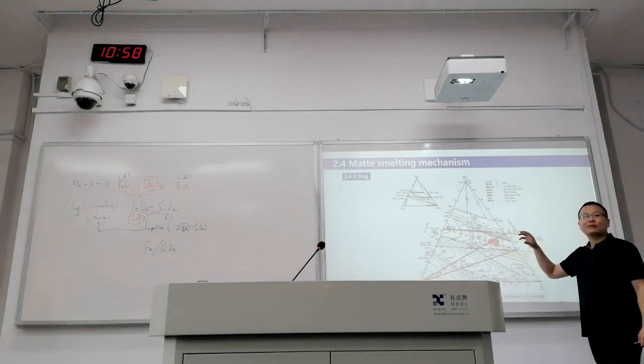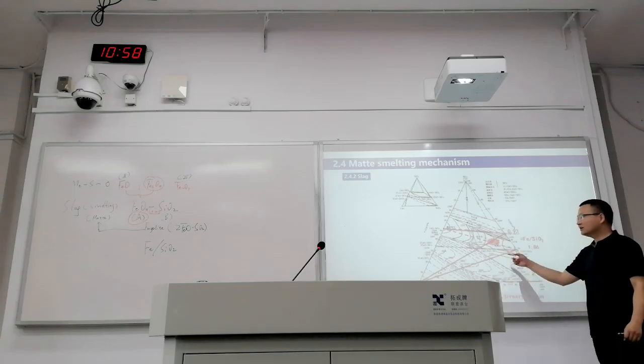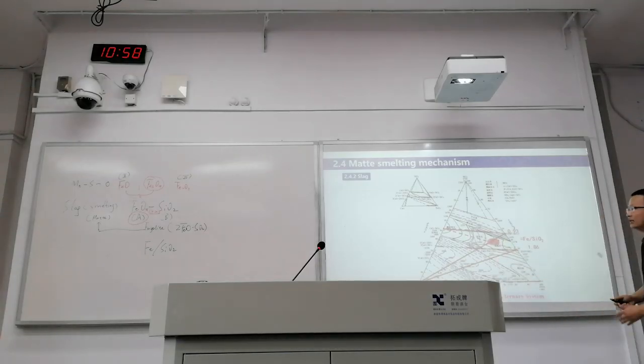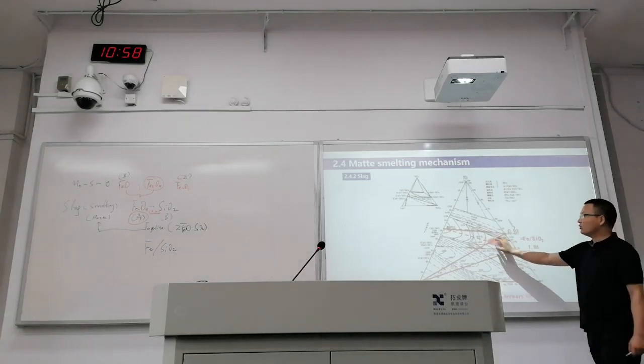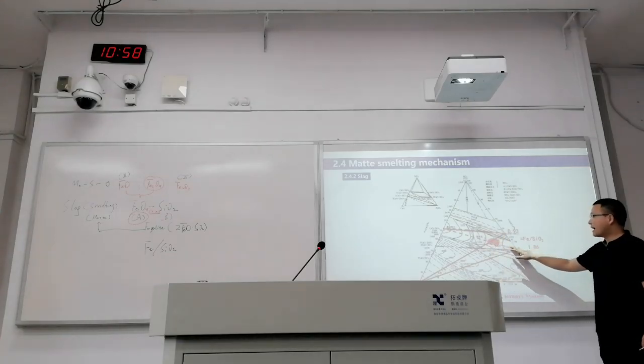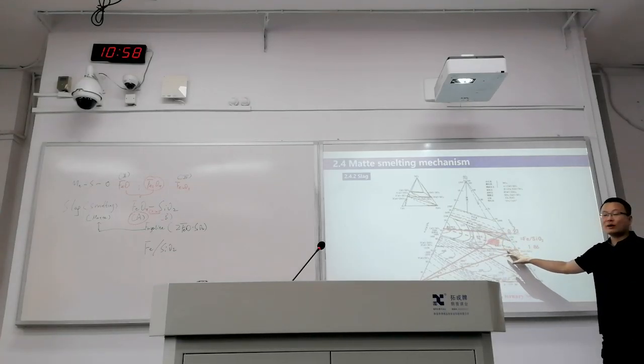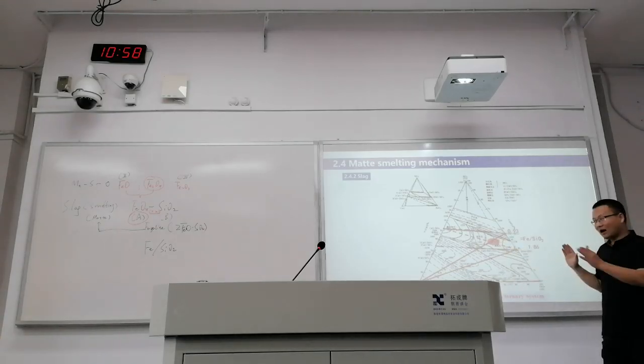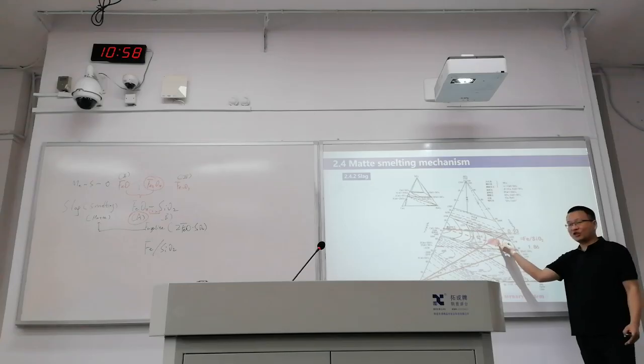region for the slag. Temperature is low, and when we are having such a position, what they are doing is adding silicon oxide. So the iron to silicon ratio will decrease. And also, they are adding calcium oxide and get the proper composition here. So this is the strategy. And the problem nowadays, we are no longer using this part. We are moving back to this region.